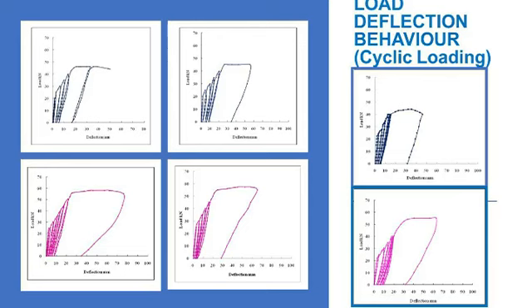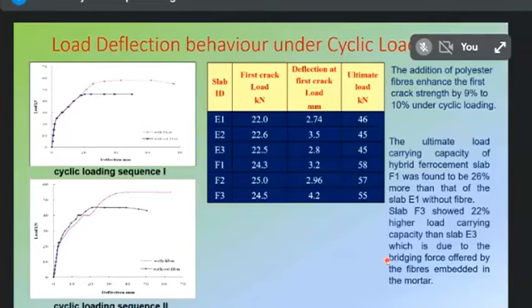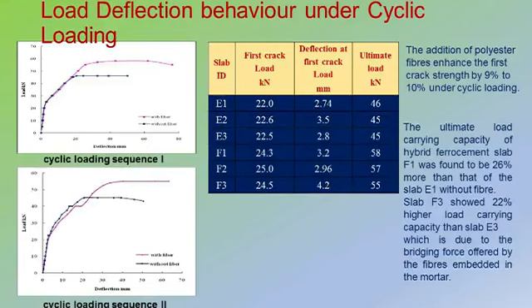And this is the load deflection behavior for cyclic loading. All these are for cyclic loading sequence 1, and this is for cyclic loading sequence 2. In cyclic loading sequence 2, we can observe that the cycles were repeated at loads closer to the ultimate load. This is for without fiber, and this is for with fiber. On comparison, we saw that slabs with fiber had a higher load carrying capacity, and the ductility was more in loading sequence 1 and in loading sequence 2.